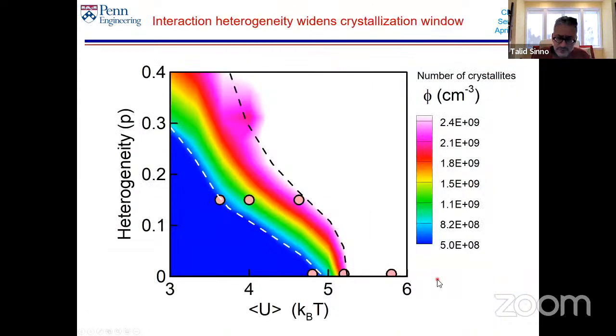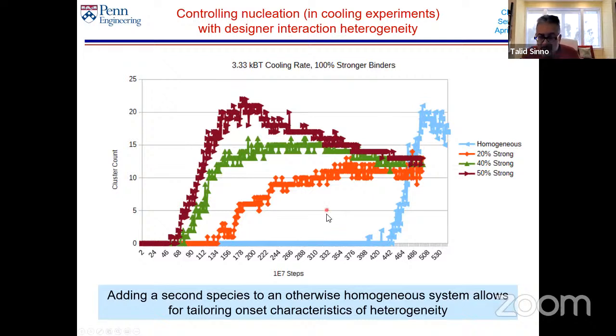And so, in the interest of time, I'm going to show you just one last thing, which is a plot of time. We didn't really clean this up, but I'll basically mention the following. This is time. This is the number of clusters formed in the system. And this cyan here is the number of clusters that form as we cool a sample. So this is a non-equilibrium simulation. You see nothing, nothing, nothing, nothing. And as we're cooling, all of a sudden the system is triggered to aggregate, and the cluster count goes up. And then it starts coming back down because clusters are joining, coalescing with each other and creating this gel.